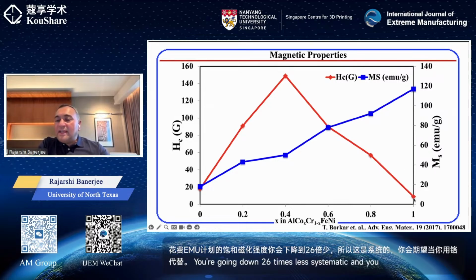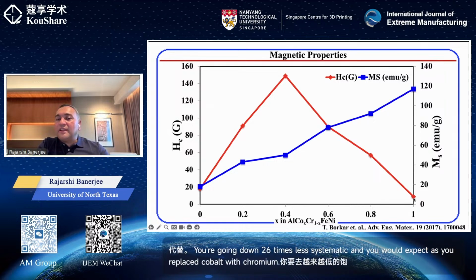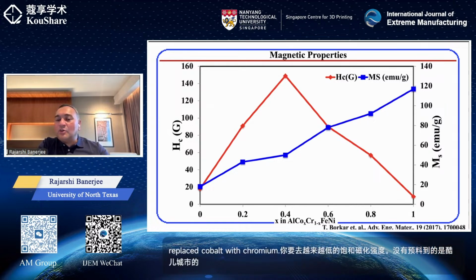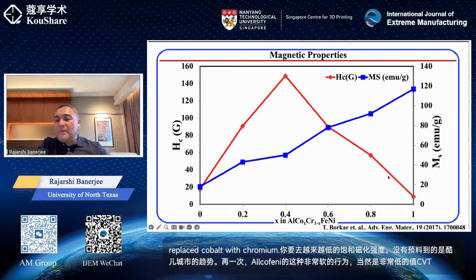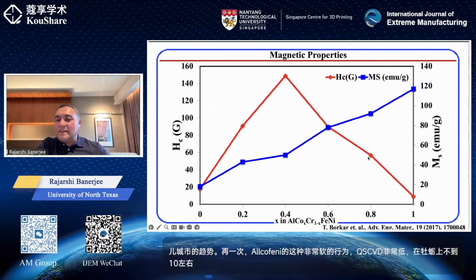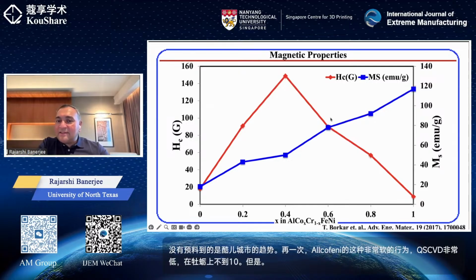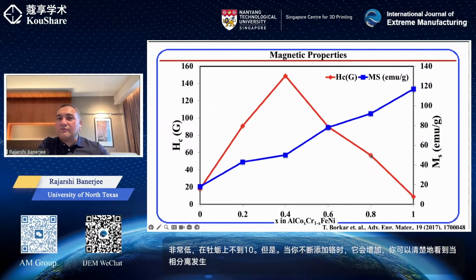On the, again, this very soft behavior of AlCoFeNi, very low value of coercivity, less than 10 oersted or so. But as you keep adding chromium, it increases. You can clearly see an increase. And this is when that phase separation takes place. If you remember, when you added chromium, you started forming initially iron-chromium-rich precipitates and then a spinodally decomposed microstructure. But it reaches a peak value.